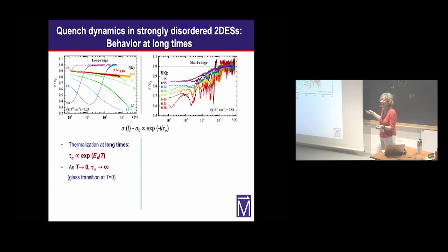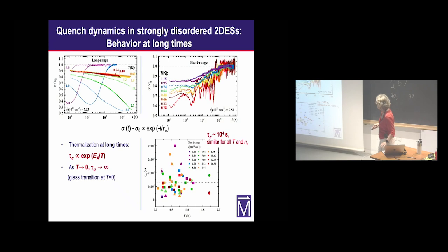So we can extract the thermalization time for different temperatures, densities, devices, and so on. And this is what we get: no systematic dependence on anything. The thermalization time is of the order of 10,000 seconds. So the question is, again, is this consistent with MBL? Here we recall that MBL should be extremely sensitive to a coupling to the external bath. Just like the other people, we cannot reduce this coupling further, but we can make it stronger.